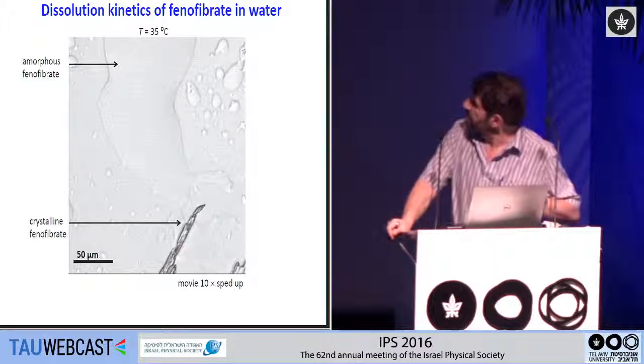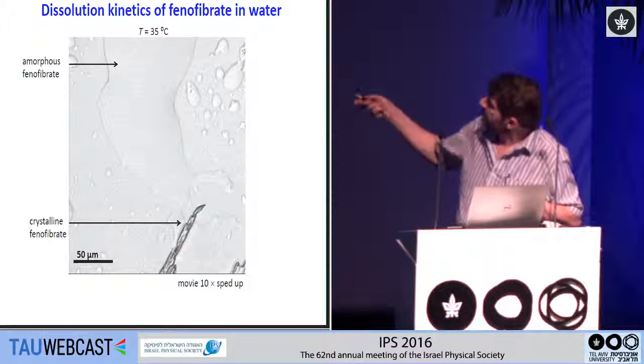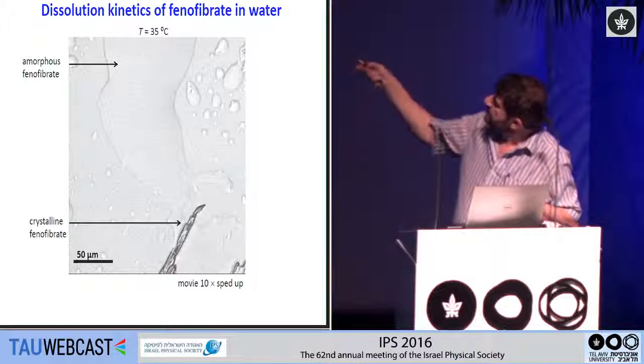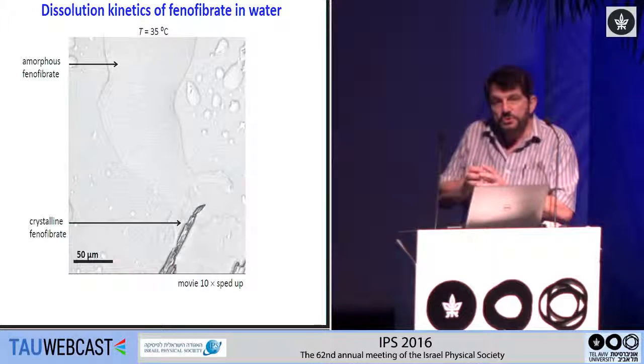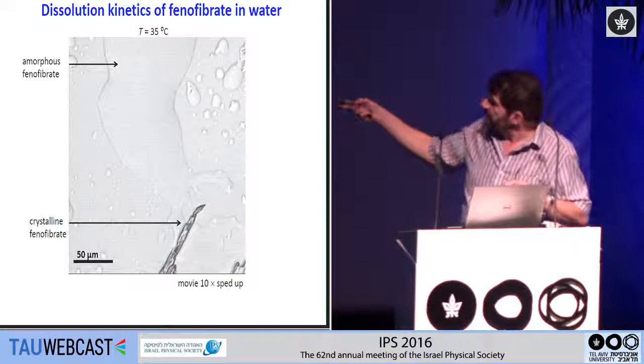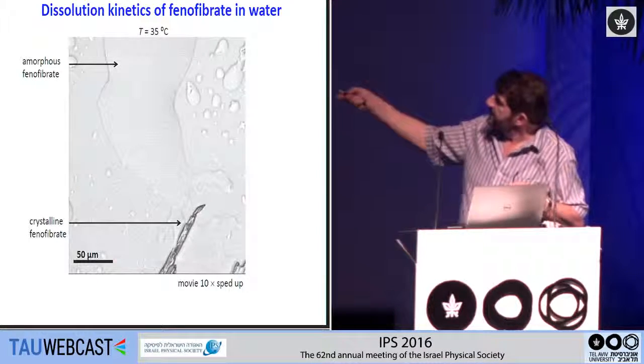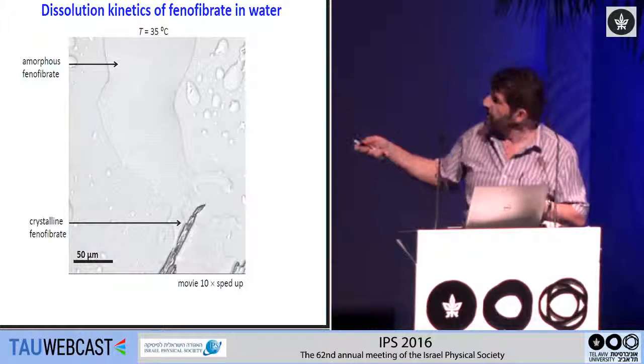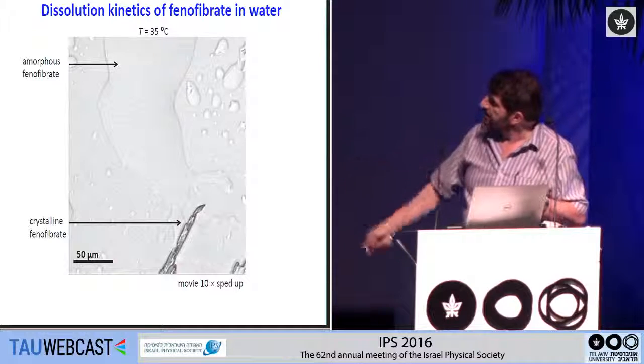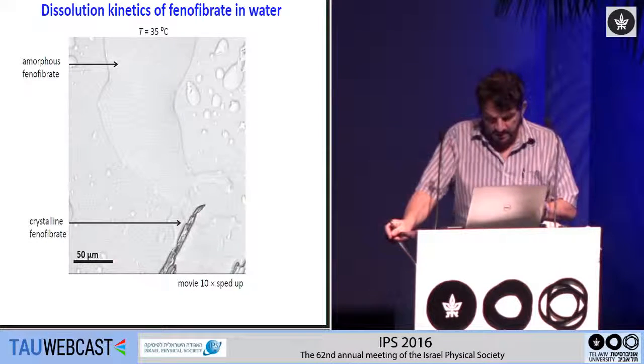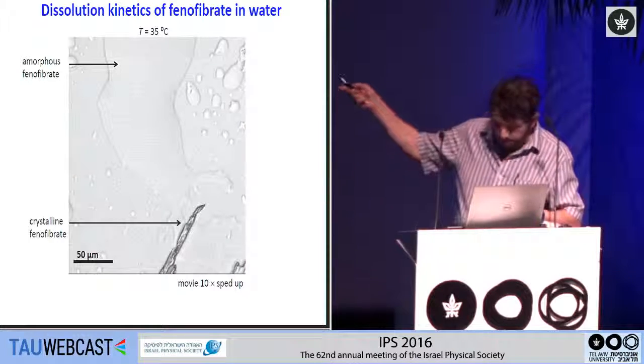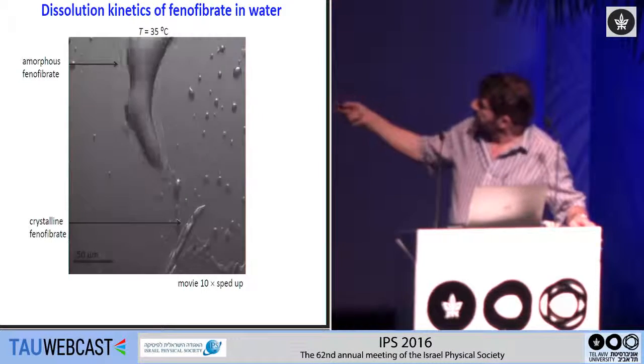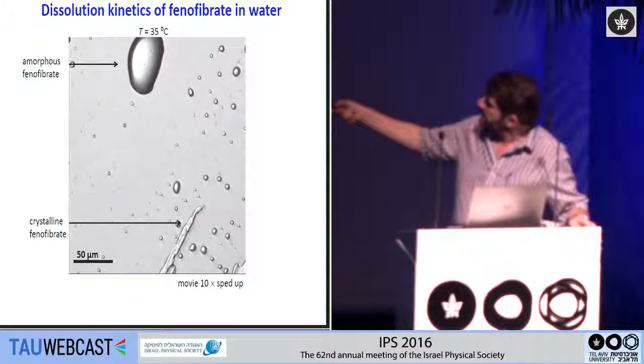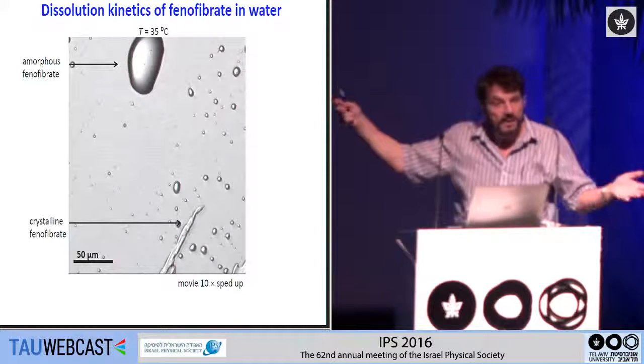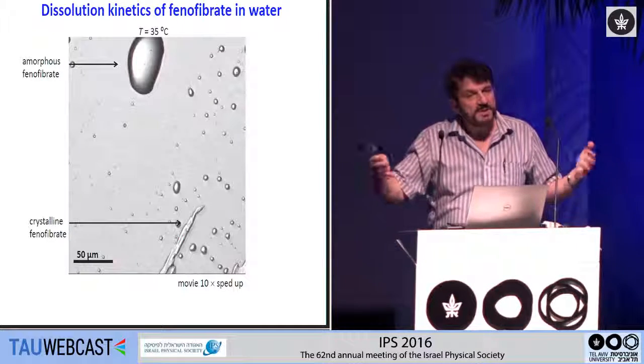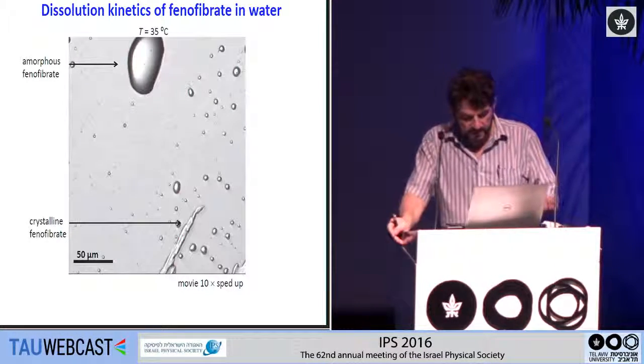In fact, you can also do a simple experiment. I'm sorry for the poor contrast here, but this is a collection of amorphous material that we collect. It's a supercooled fluid, an amorphous material that normally wants to be crystalline, but we've maintained it amorphous by collecting this spray-dried material. The actual material is fenofibrate, which is a generic drug that's very strongly crystalline, and if we just put a drop of water on, you can see that this doesn't dissolve, but this completely dissolves. The water just dissolves it. And that shows that the amorphous material is much more soluble in water than the crystalline material.